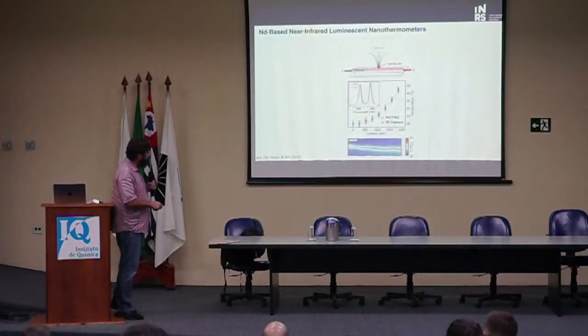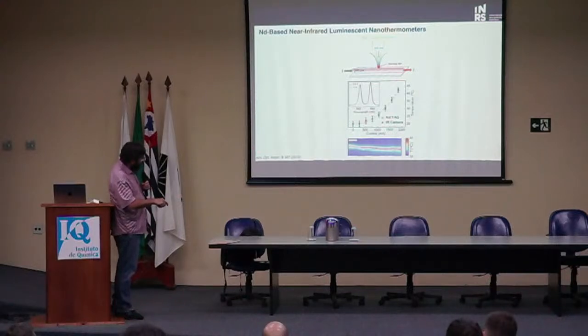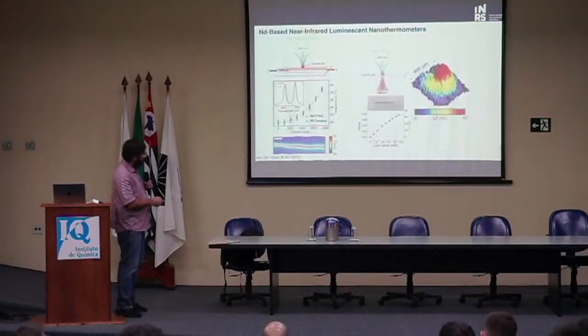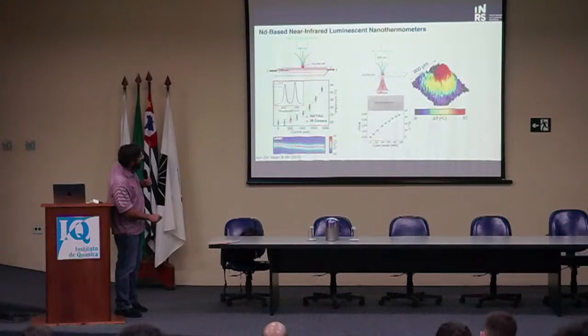But just to show that it worked, this is a tungsten wire on a surface. We run a current through it. Of course, our nanoparticles are spin coated here. When we run the current, we see where the hot spot is, of course, is where the current is passing. We've looked at microfluidic channels. In this particular case, we're using 1500 to heat a channel containing our nanoparticles. And when we heat, the water absorbs. And then we use 800 to map. And of course, we see the hot spot is at the focal point.